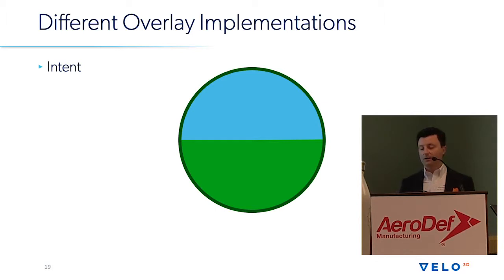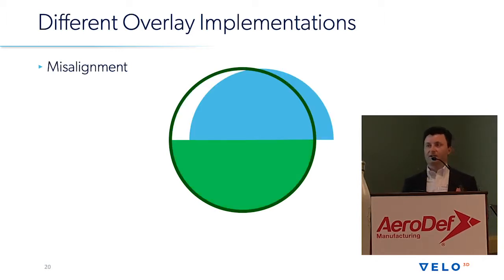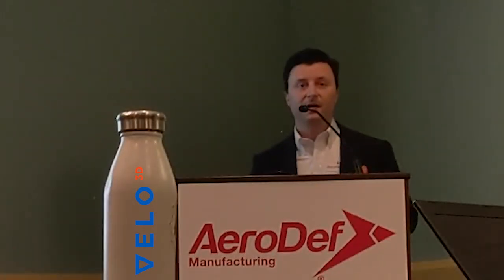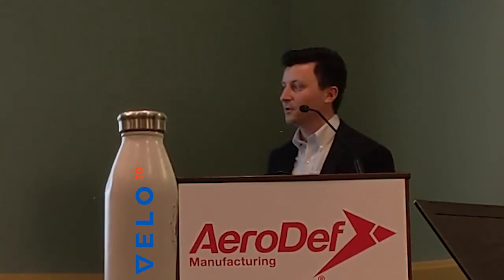There's one issue that you need to be aware of, though, which is it doesn't solve the problem. If your core shifts, if one of your lasers is moving relative to the other one, what this does is it can mask the overlay mismatch that you see when your contours are stitched up together. And as a result, what you really end up with is a subcontour porosity, which can be a sharp, jagged porosity, which is a real killer when it comes to high cycle and low cycle fatigue. So just because the part looks good on the outside with a single contour scheme doesn't mean the part is necessarily good. Doesn't mean it's necessarily bad, but it's something to keep in mind when you're looking at different ways to approach multi-laser assignment.